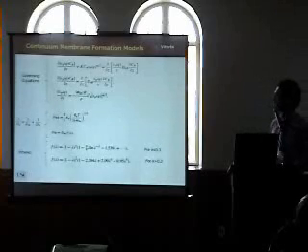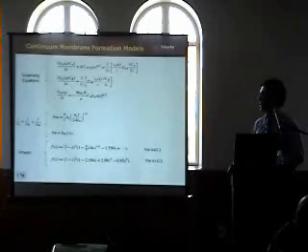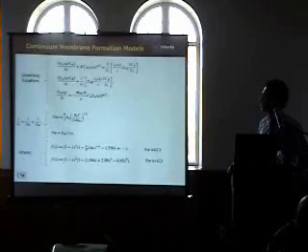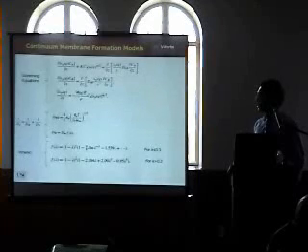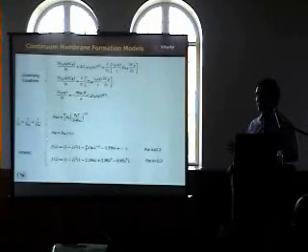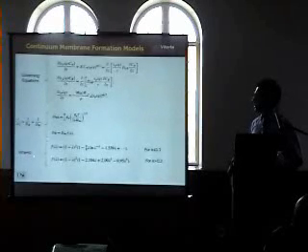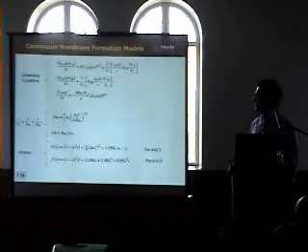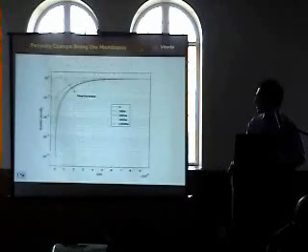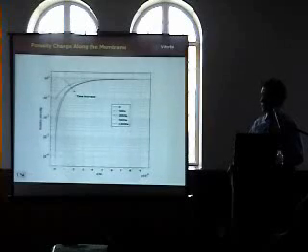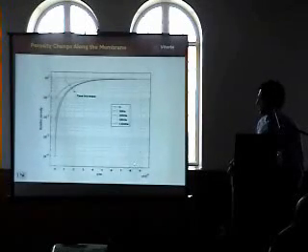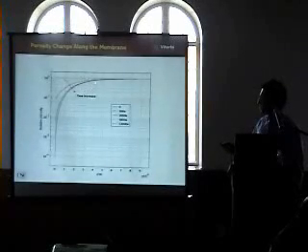To better understand the CVD process, we tried to model the transport of these gases during deposition. We solved the governing equations using the finite element method with adaptive computational time steps and adaptive computational grid size, in order to capture the most changes where pore size changes most. We used two different diffusivities: Knudsen and hindered diffusion. We saw that most of the changes in porosity and pore size happen at the first two micrometers of the membrane, as shown by the relative porosity versus membrane thickness plot.